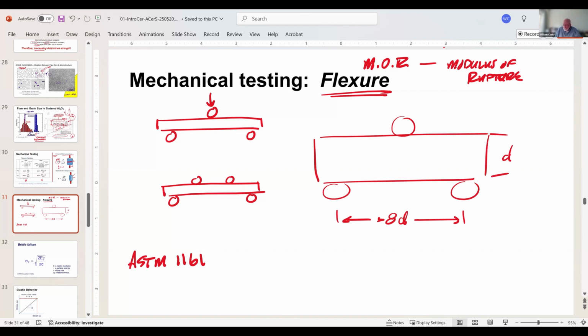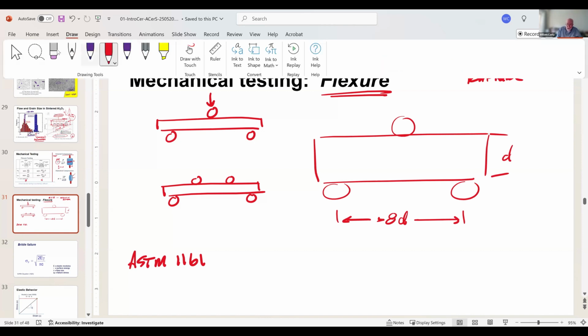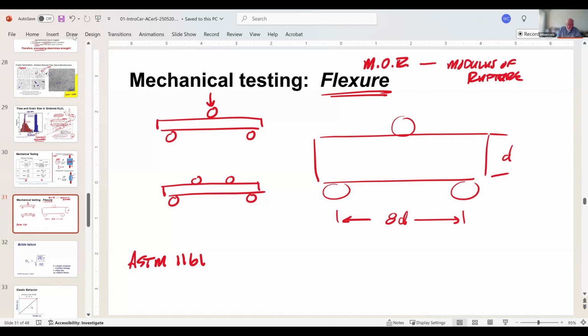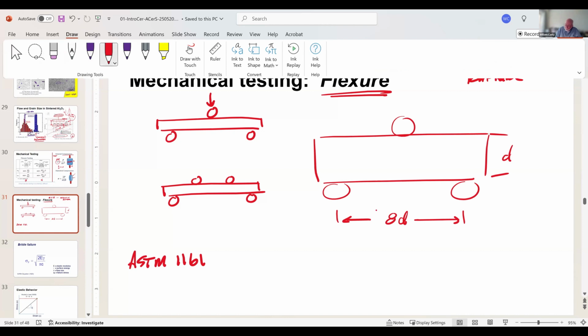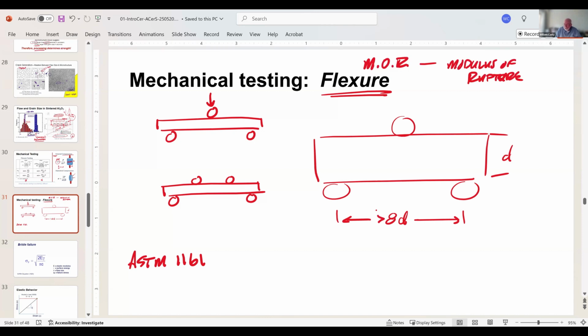If you're less than 8 times D, you have a problem and you get what's called a short beam shear test. So it must be at least 8 times D, the length of this span on the lower limit. What you get in this specimen is a neutral axis down the center. Okay, so this side is tension, this side is compression. So what that means is in my specimen, my greatest tension is down here along this axis, and I get 0 tension in here. So I have small tension in here. As I go up, you could argue it's going to be essentially a triangle.